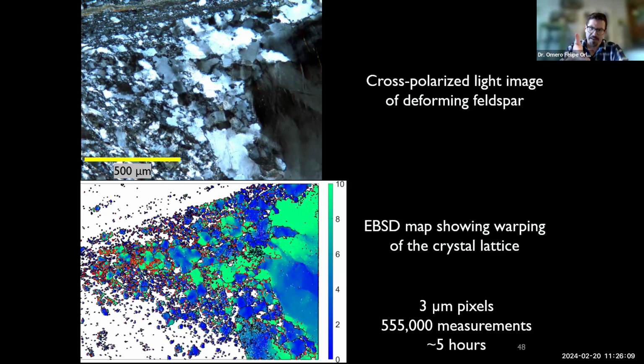And so you end up with these maps, right? Like this one below you, showing you the orientation of the crystal lattice in a really tiny spot. I mean, a sub-micron area. And you can get 555,000 measurements in 5 hours by stepping the beam 3 microns and measuring at each point where the crystal lattice was pointing. And in our case, this is simplified because it's all potassium feldspar recrystallizing here. But the color scale that you see has black lines for what you'd consider a normal grain boundary, red lines for a low angle grain boundary or a subgrain. And then the blue to green scale is showing you how misoriented, what the difference in orientation is between that spot on the crystal and the mean orientation of that whole crystal, right? So you're seeing the warping of the crystal lattice away from the general orientation of the grain due to the activity of dislocations and crystal plastic deformation.